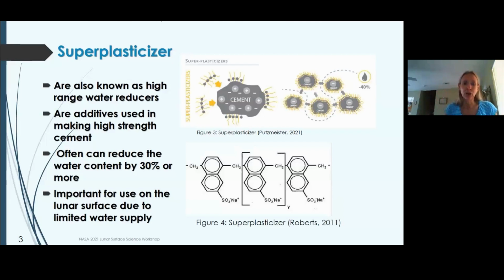And you can see the chemical structure of a particular kind of superplasticizer. If you look at the top, you can see that these superplasticizers have ions in them. They surround cement particles and separate them. And if you have the cement particles separated more, you're able to get a higher strength structure from them. So that's kind of what superplasticizers do. Next slide, please.